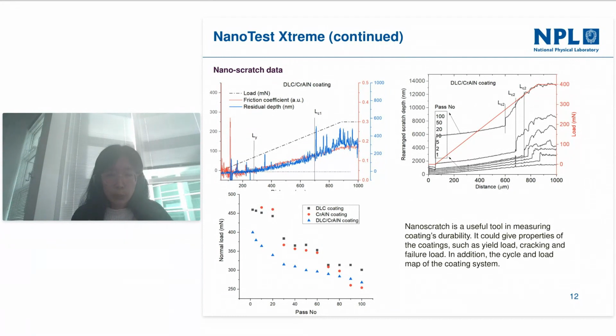And we have done this test on a selection of coatings, and by changing the ramping load and also by combining the multi-load and also the scratch passes, we can develop a map of the material's wear resistance of the coating. So we think it's a useful tool in measuring the coating durability, and gives us properties including the intrinsic and the fracture behavior.